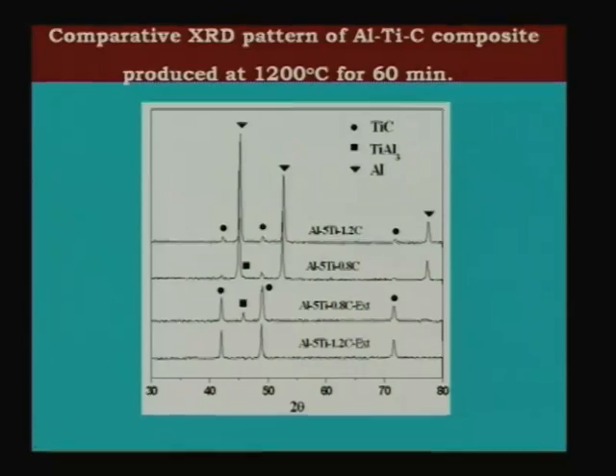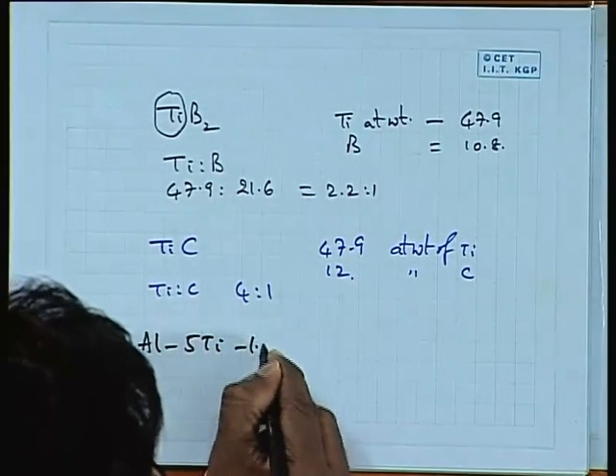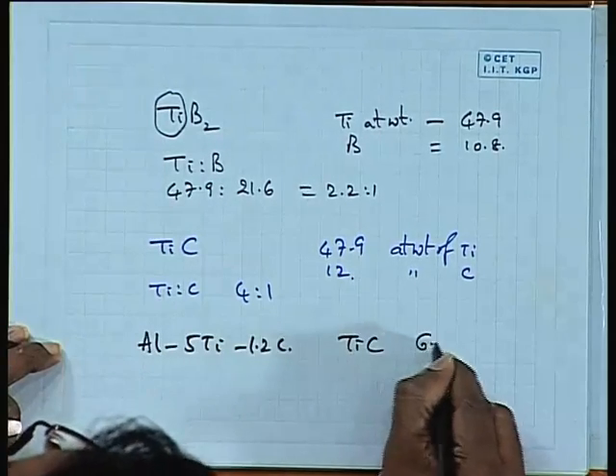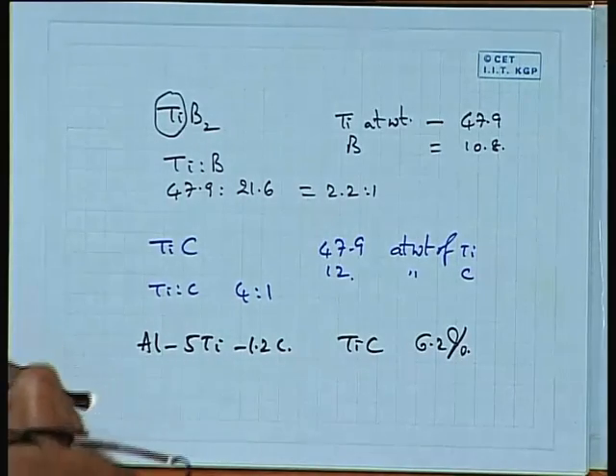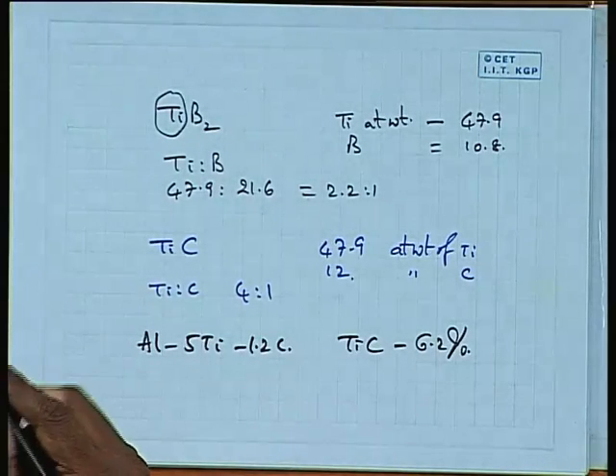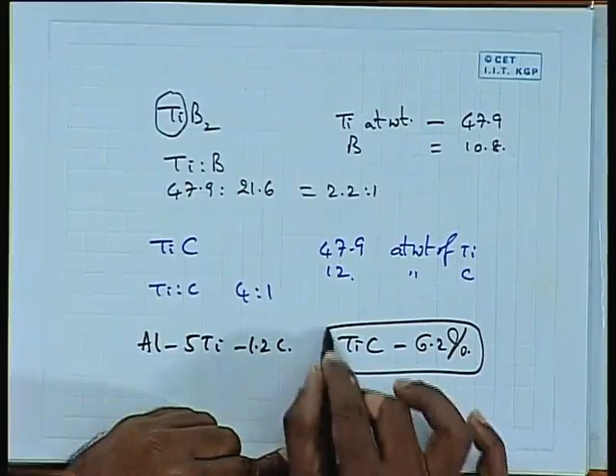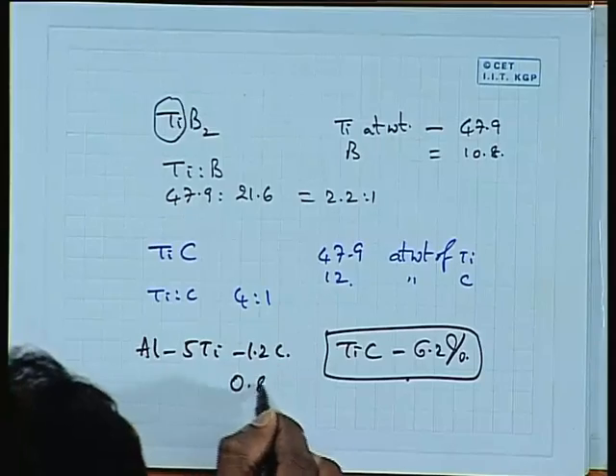You are taking a composite of aluminum, 5% titanium and 1.2% carbon. So, how much is the TiC? TiC is 6.2%, 5 plus 1.2, that is the TiC. So, weight percent of TiC is 6.2%, and we know X-ray has a limitation. Whenever you have a volume fraction of a phase which is very low, you cannot see those peaks. So, if at all there is some TiAl3 also that has formed in this composition or in that 0.8% carbon composition, the TiAl3 volume fraction will be so small, because only after the titanium reacts with carbon, whatever titanium that is left out, that alone will react with aluminum and give you TiAl3, because TiC again is much more stable than TiAl3 thermodynamically. So, as a result, the first preference of titanium is to react with carbon.